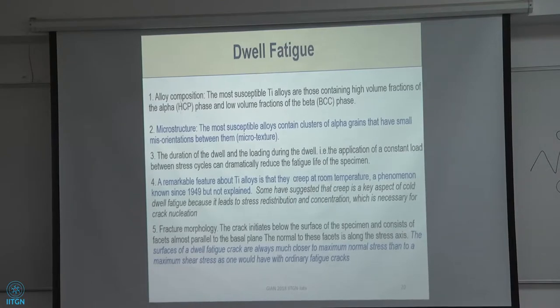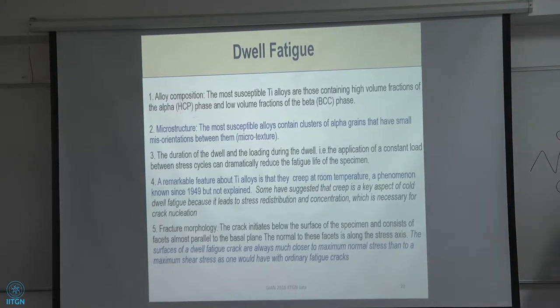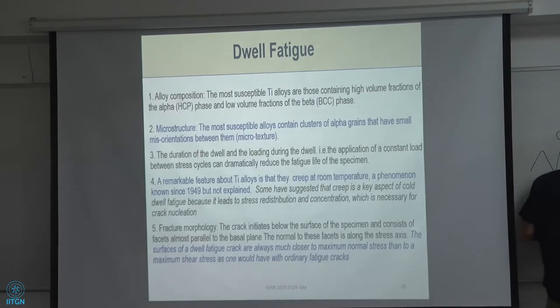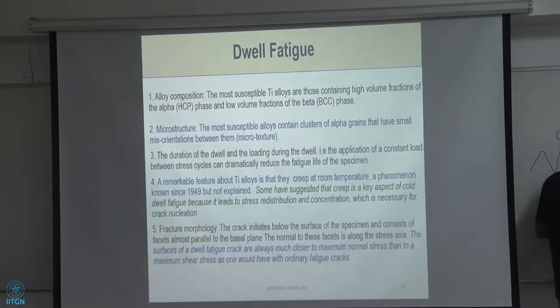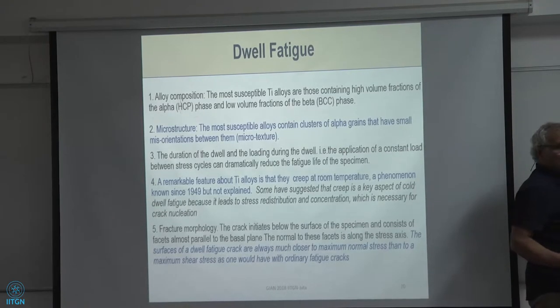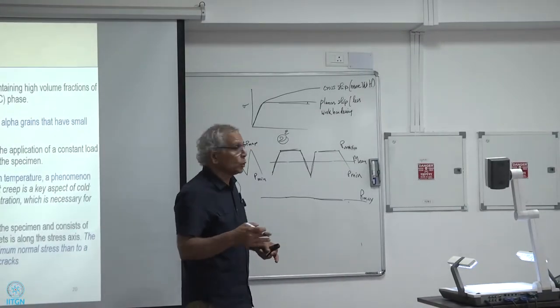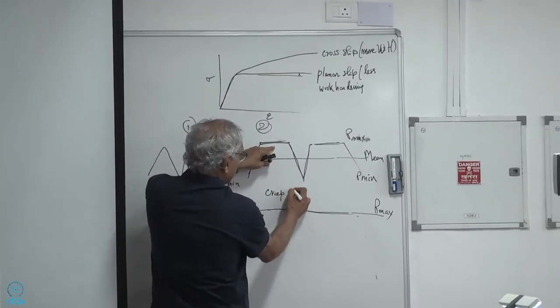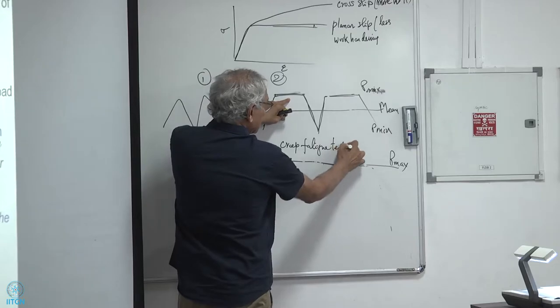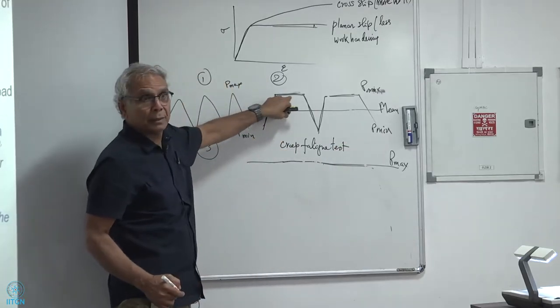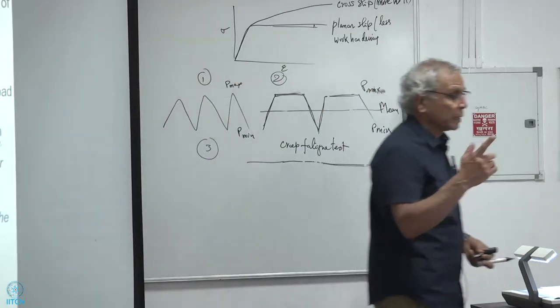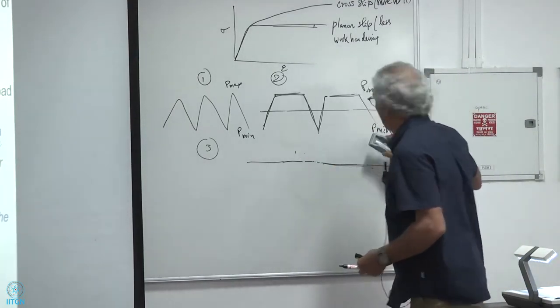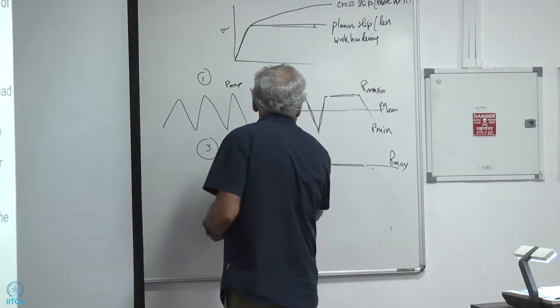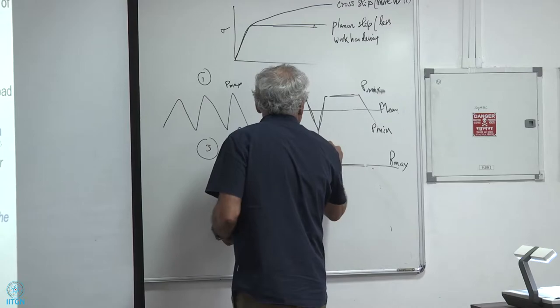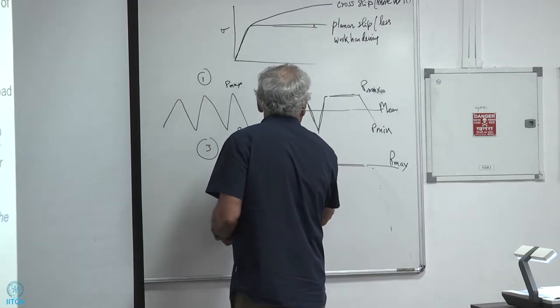So there is your Andrade creep. And in that formulation of Andrade creep, alpha happens to be 0.2 here, okay? These are room temperature creep studies. And then in the case of Neeraj and those guys, I think the slope was a little bit different, actually. Unusual creep behavior in the titanium alloys. This is based on strain rate sensitivity.